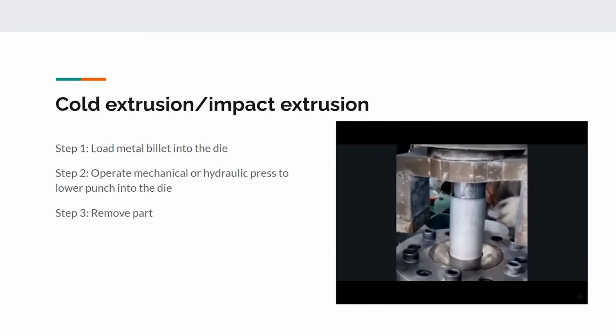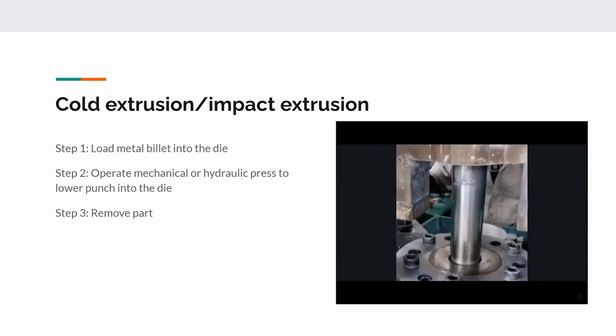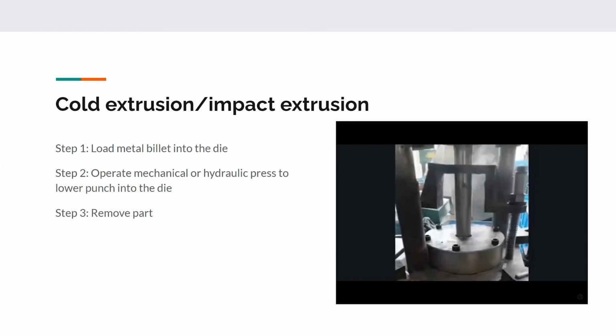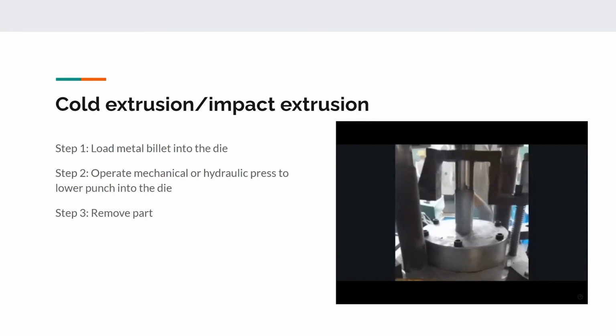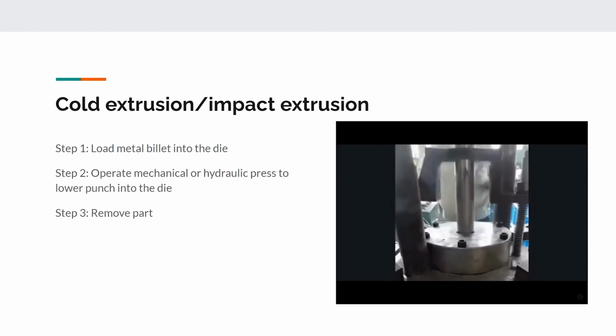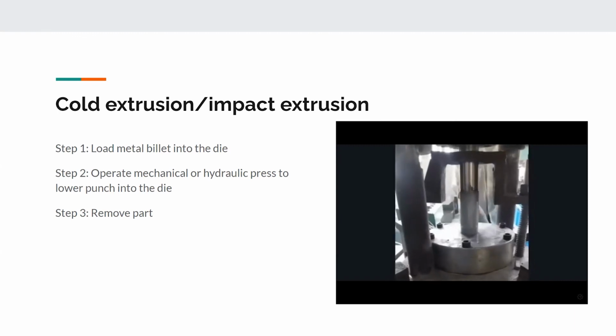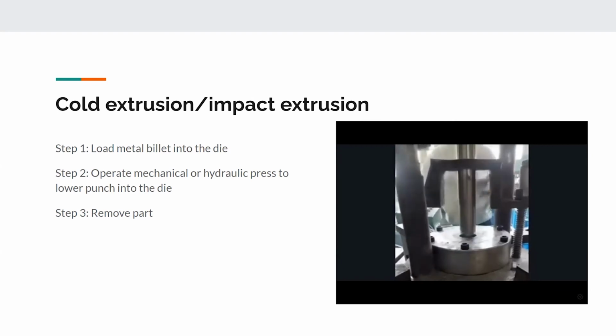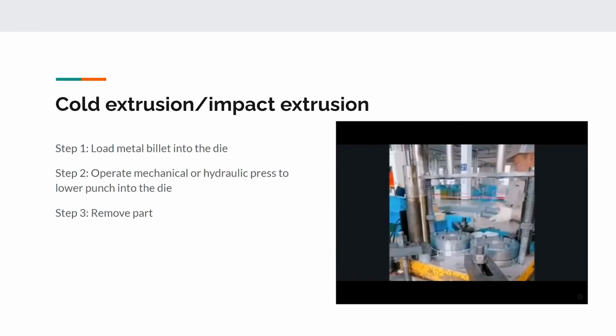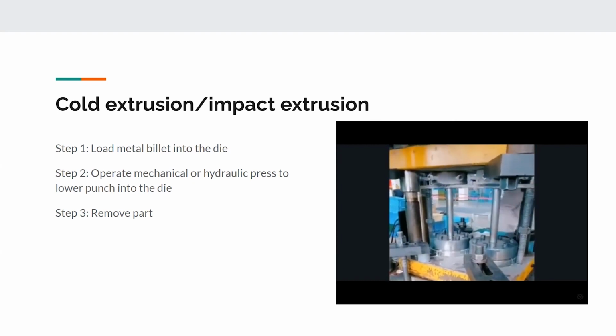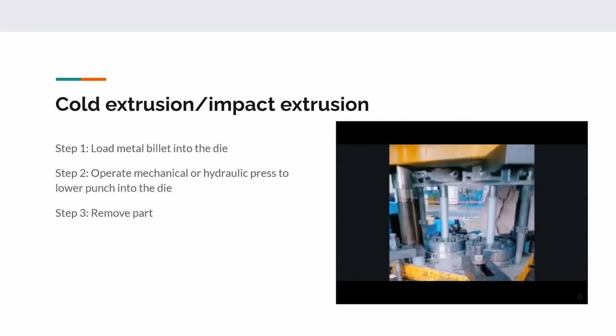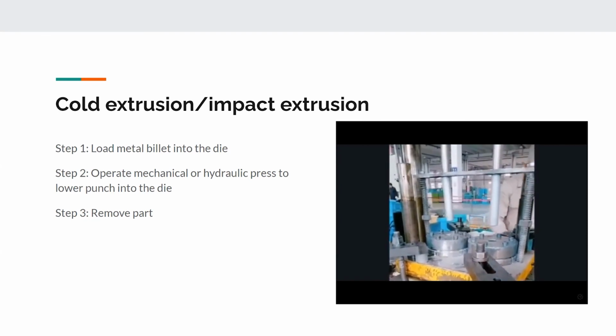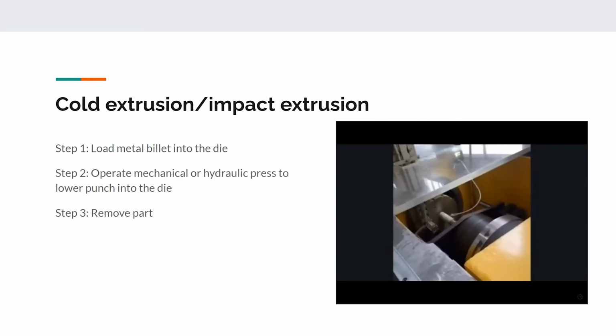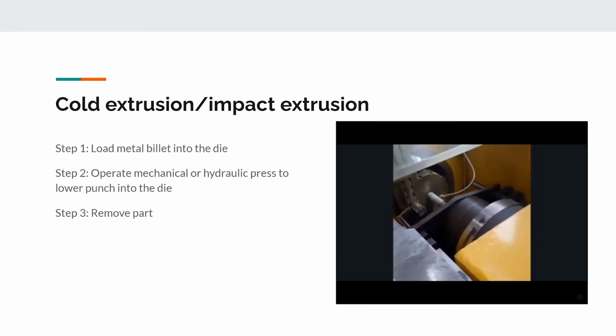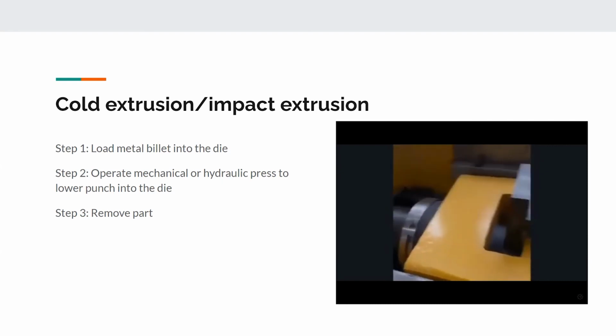The steps for impact extrusion are: load the metal billet into the die. Next, operate the mechanical or hydraulic press to lower the punch into the die. And finally, remove the part. When compared to other extrusions, impact extrusion operates at a higher speed with shorter strokes, allowing up to 60 parts to be done in 1 minute. This allows the final piece to be high in hardness and yield strength due to strain hardening, with a good surface finish and tight tolerances. The impact extrusion you see in this video is considered a discrete process because one part is produced per extrusion cycle.